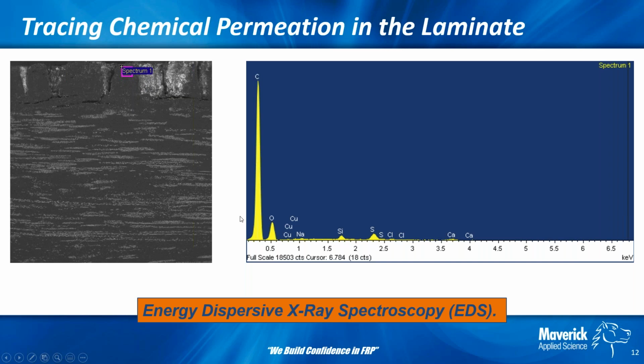And then looking to the right-hand side, this is the scan of that area. This shows all the elements that we're picking up in that area, and also the magnitude of those. So you see carbon, which we find in almost everything, oxygen, copper, which probably comes from some of the resin additives, sodium, silica is the glass, and over here is sulfur. You see chlorine and calcium as well. But we're most interested in sulfur, so we can actually measure the degree of sulfur that is present at that specific location.